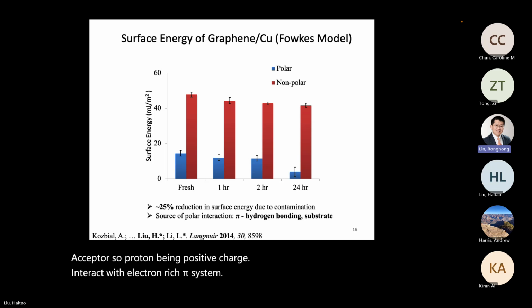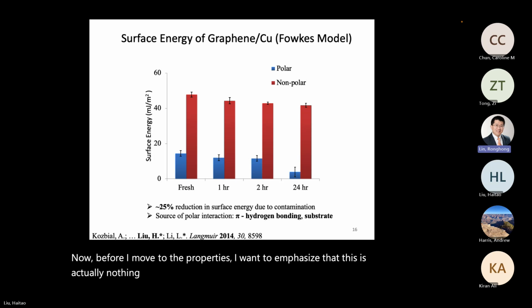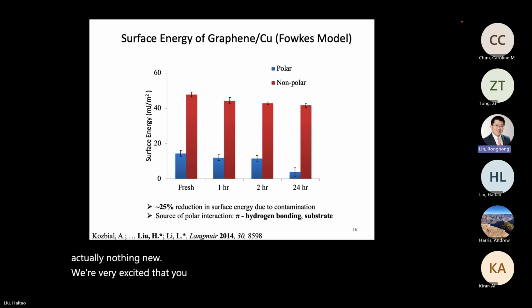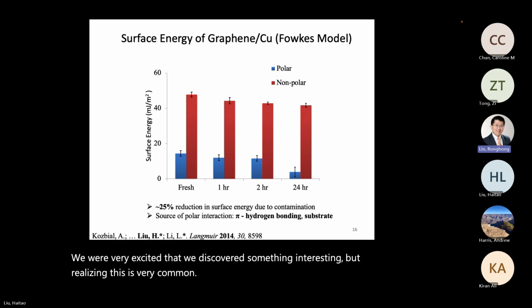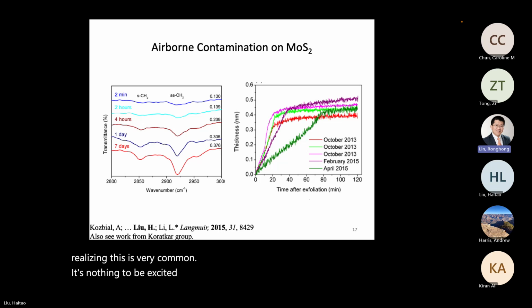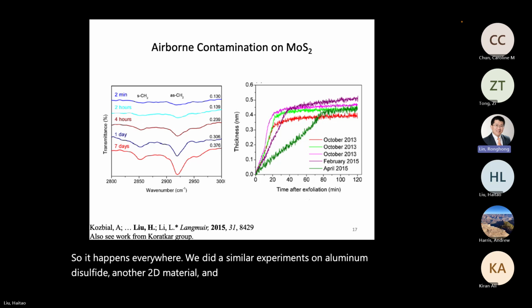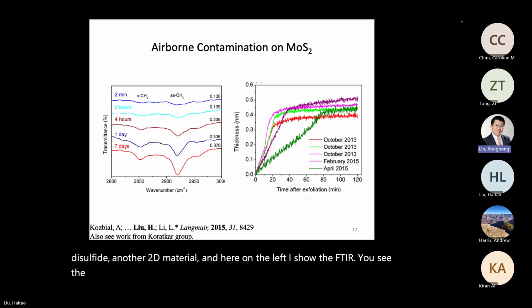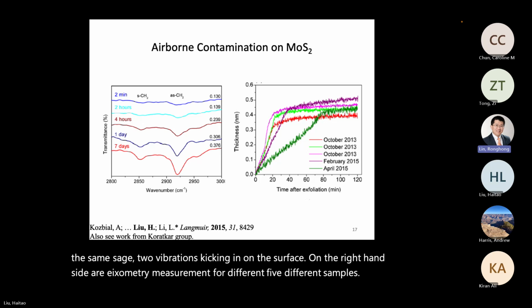Now, before I move to the properties, I want to emphasize that this is actually nothing new. We were very excited that we discovered something interesting, but realizing this is very common is nothing to be excited about. So it happens everywhere. We did similar experiments on molybdenum disulfide, another 2D material. And here on the left, I show the FTIR. You see the same CH2 vibrations showing up on the surface. On the right-hand side are ellipsometry measurements, 5 different samples. You see the same kind of feature of linear growth and saturation around 0.5 nanometer.